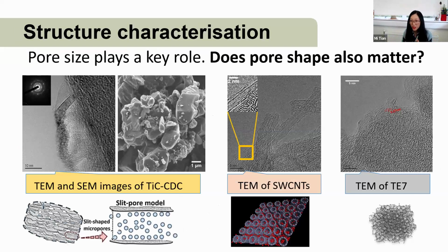And we know the pore size plays a key role. We need to keep the pore size smaller than 1 nanometer. Does the pore shape also matter? To answer this question, we selected 3 different pore shapes. The slit-shaped pores, we can see the few layers carbon sheets represent slit-shaped pores. And we also have the single-wall carbon nanotubes representing cylindrical pores. And also the completely amorphous carbon.